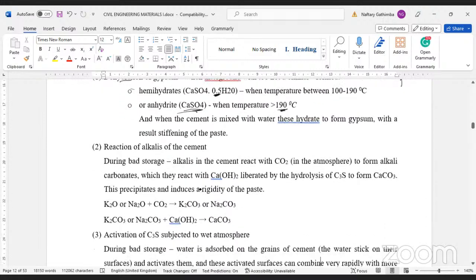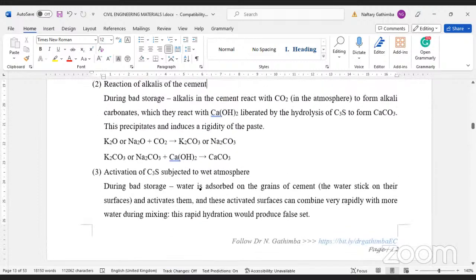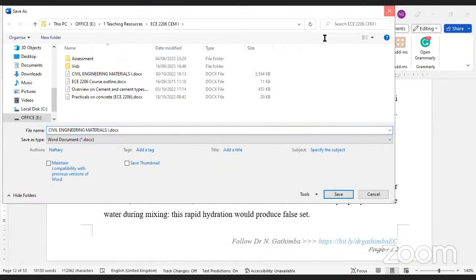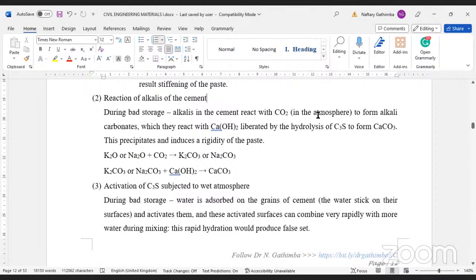Of course, the other thing we are saying is reaction of alkalis of cement. In cement, we have silicas, we have sometimes potassium, sodium, calcium alkalis, the hydroxides. So if our cement is stored badly, it may react with carbon dioxide in the atmosphere, resulting in formation of carbonates. And we are giving an example. For example, if our cement has calcium oxide, potassium oxide, or sodium oxide, it may react with carbon dioxide to get the carbonate. And this will precipitate out from our mix, causing our cement paste to become rigid, setting to occur. So false setting, we can remix that.